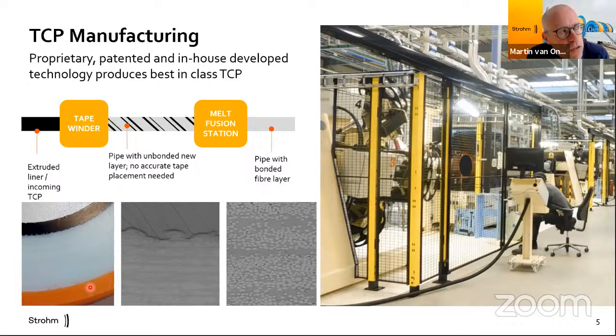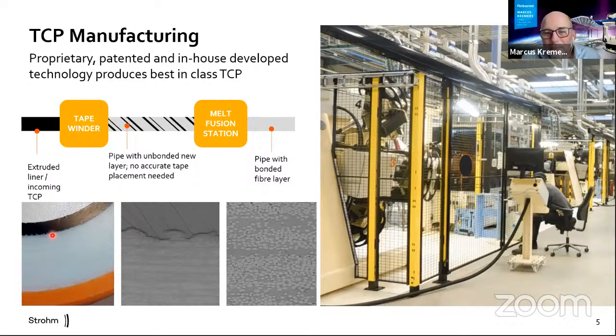We are using adhesives in a system where we use what we call a permeation barrier in hydrogen, which is aluminum wound, where between the liner and the fiber pack we have an aluminum barrier wound. There we do use an adhesive system. In our end fittings, we simply clamp our end fittings. That's one of the nice benefits of polymers. They are ductile, so they allow us to simply clamp our pipe like a garden hose. Does it answer your question?